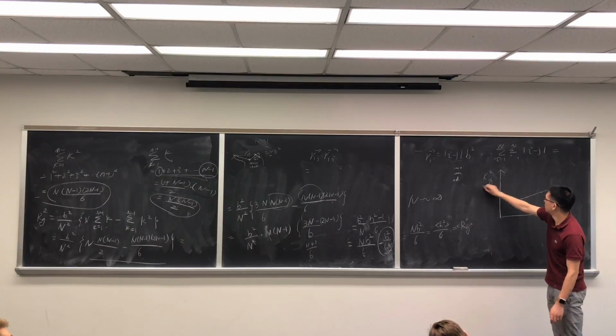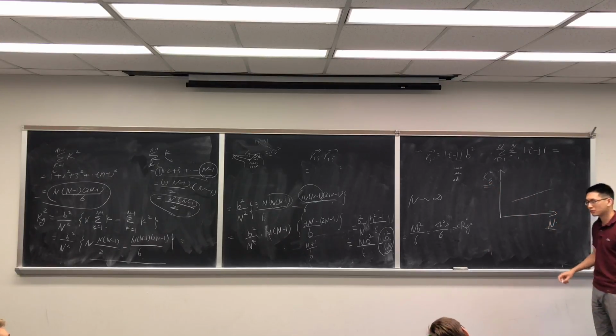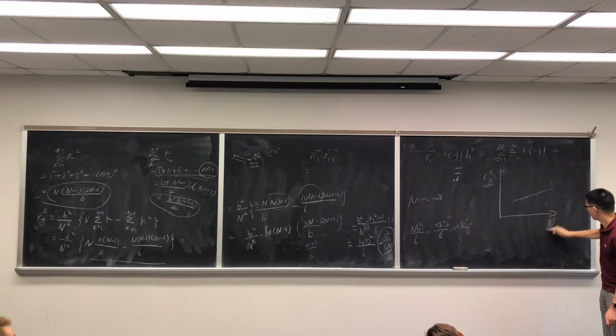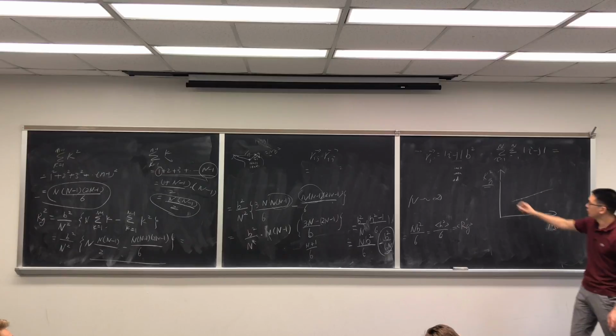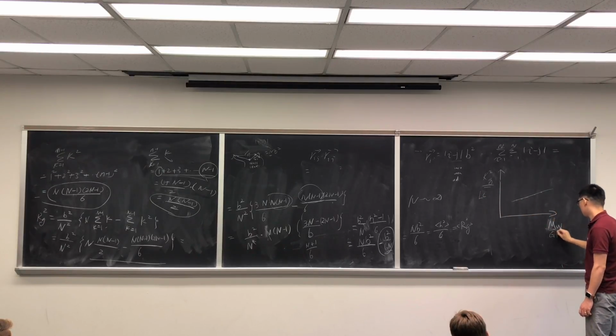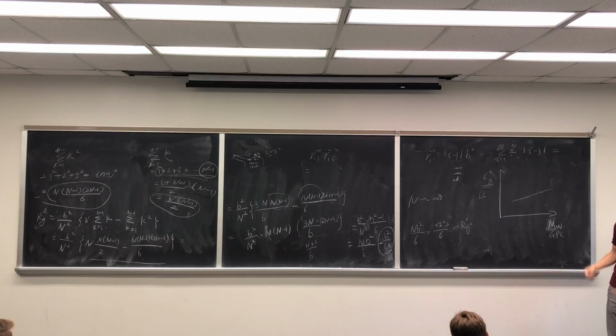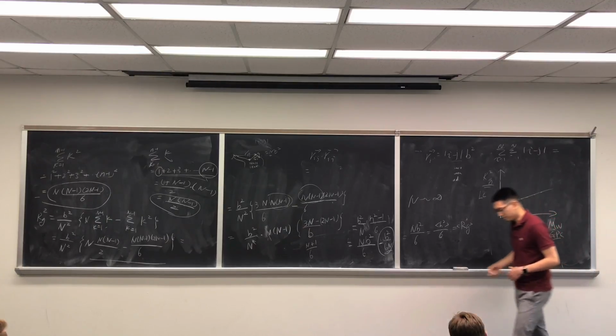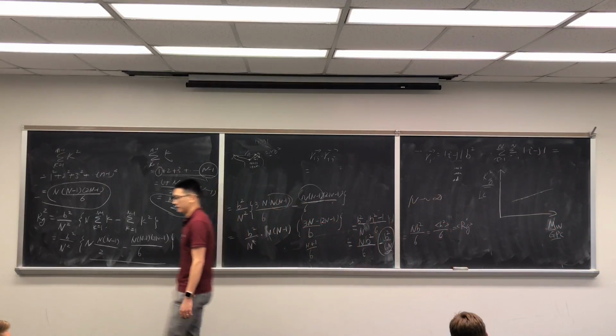This is a measurable. Molecular weight is measurable, right? You can measure the molecular weight. You can measure the Rg. This is by light scattering. This is by GPC. So you can get a relationship between these two. And a lot of the time you will get a relationship between them.